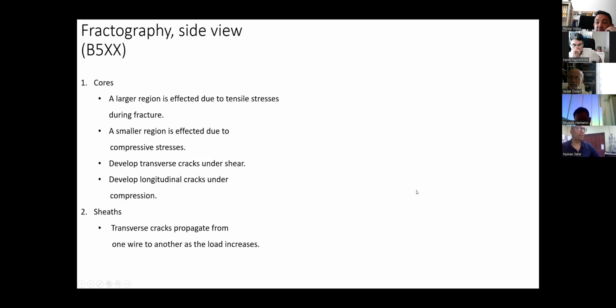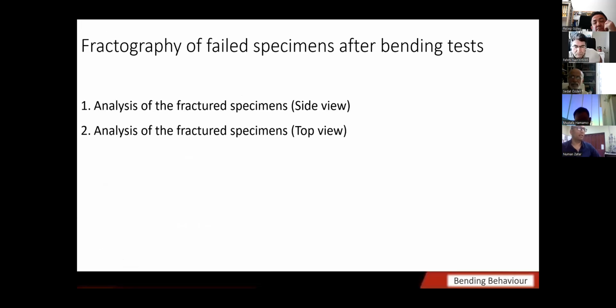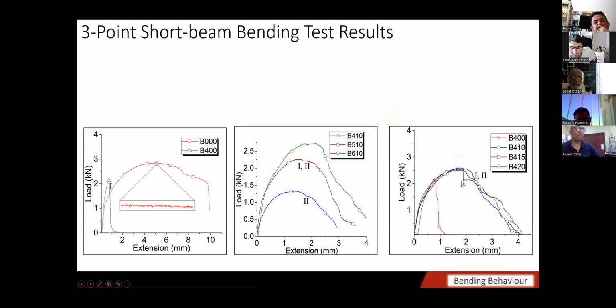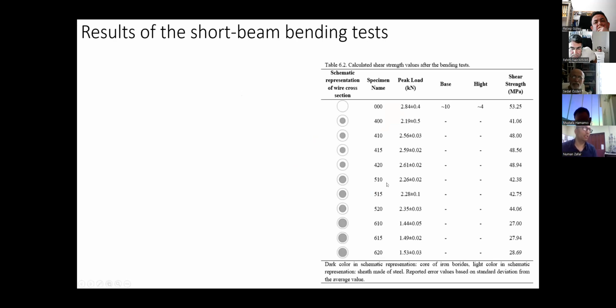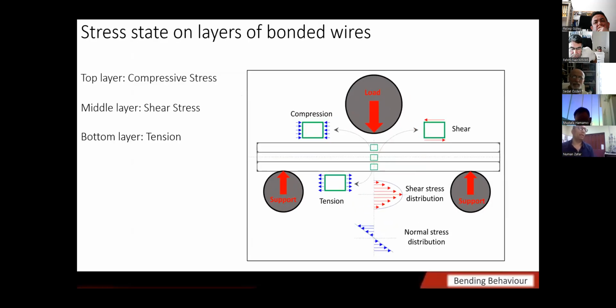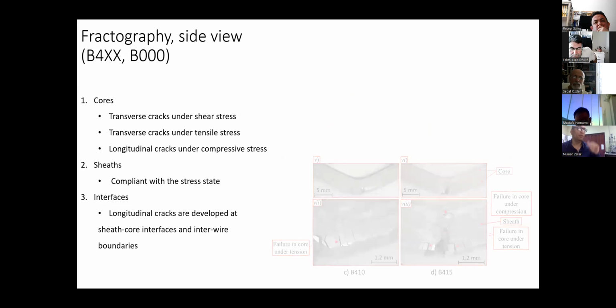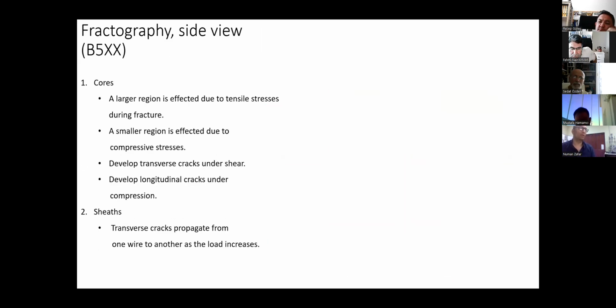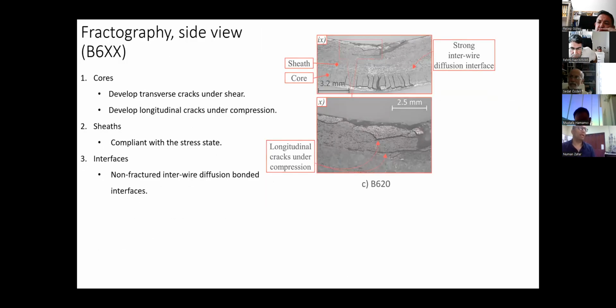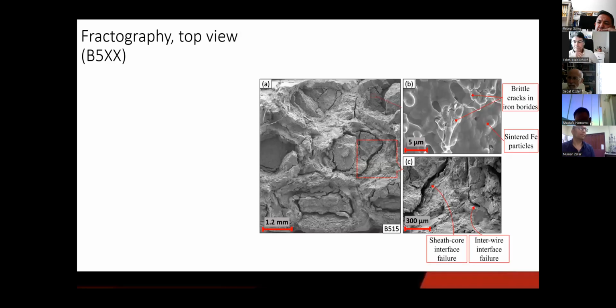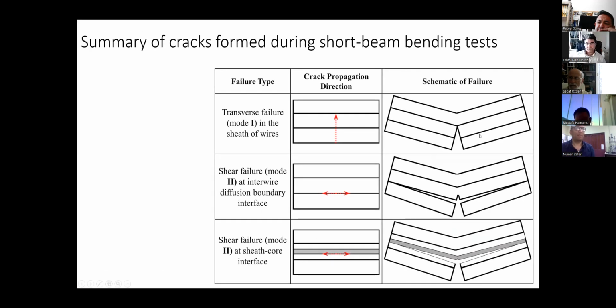Such an immediate failure in the material will result in a sudden decrease in the load value, which is seen here, right here, something like this, but they have to be in synchronization so that all wires can fail at the same time. So there is a sudden decrease in the load value. So all these modes which I have explained here are mapped on the graphs if someone wants to see what type of failure might have occurred in the material.